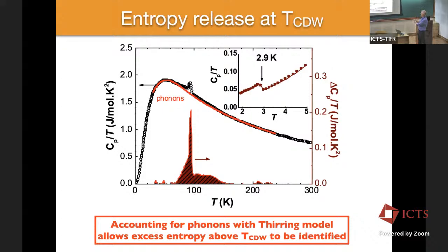But you can see that when you get up to higher temperatures, there's a very sharp anomaly associated with the 94 Kelvin transition to long-range order of the charge density wave. But if you do an appropriate analysis, which I'm going to tell you about now, which is that you try to smoothly connect the region well below the clear sharp phase transition and well above the clear sharp phase transition. And there's more than one way to do this. We're using a technique that's referred to as the Thirring method, or a Thirring model, to account for the phonon contribution to the heat capacity. Like I said, other people do different things, but the basic idea is that you're trying to smoothly connect this region of the heat capacity with this region of the heat capacity.